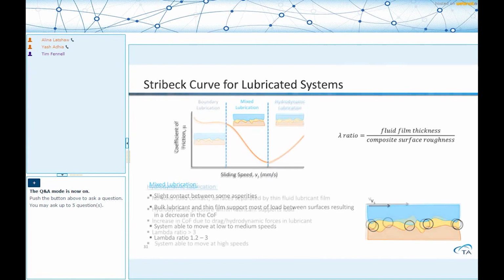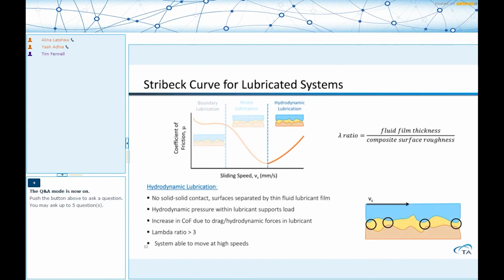And as you increase the speed further, now with these fluids, there's no solid-solid contact. Now, I would say just lubricating it, there is another opposing force, that is the hydrodynamic force of the lubricant. So think about it this way: if you have something that is extremely viscous between the two surfaces and you move into the hydrodynamic lubrication regime, that viscosity of that material is going to offer some resistance to the motion of this material. It's what we can think about as a drag force of sorts. And so while the friction is still lower, there is a higher coefficient of friction.